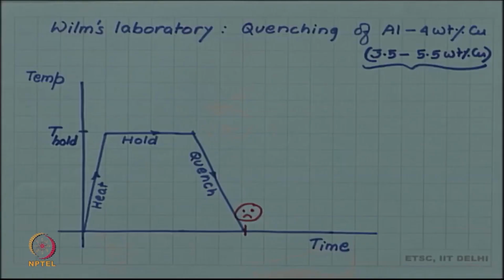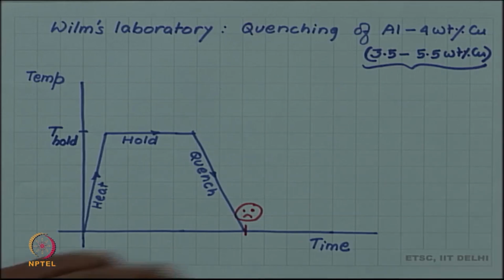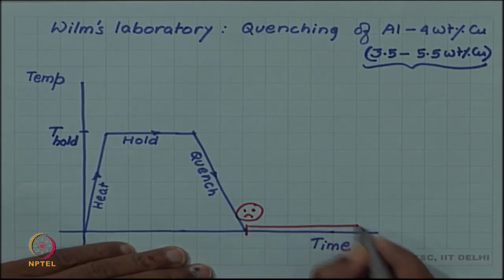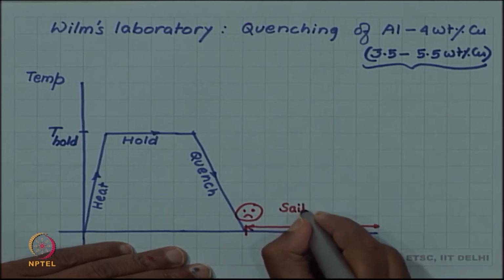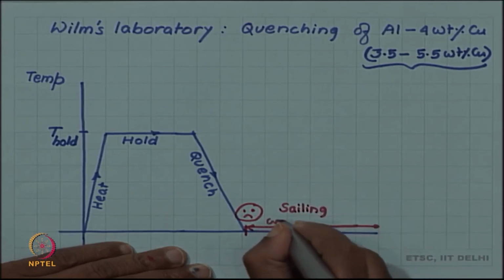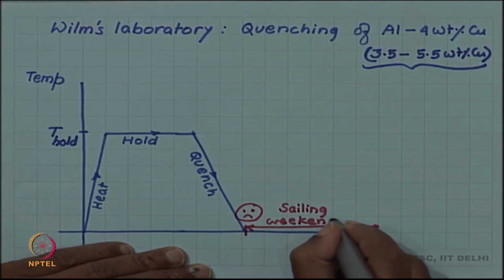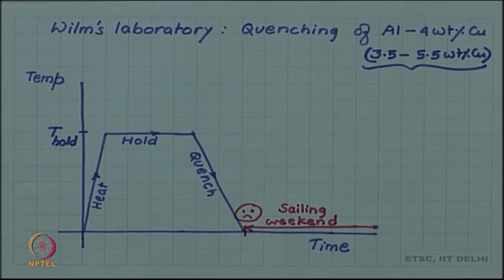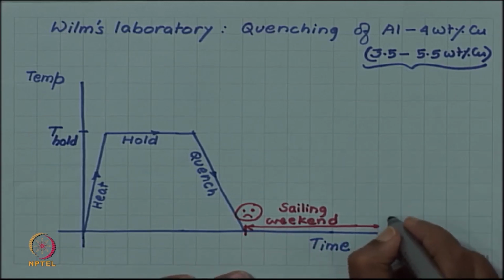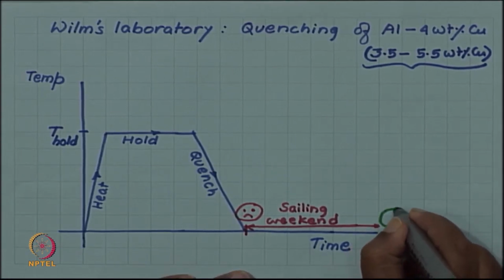Is it because he quenched the specimen on Saturday and is measuring the hardness on Monday, that is, he is allowing this period of weekend that hardness is increasing? So, he did again a control experiment where he quenched and deliberately waited long enough time to measure the hardness, and he found that yes, hardness is increasing simply because of waiting.